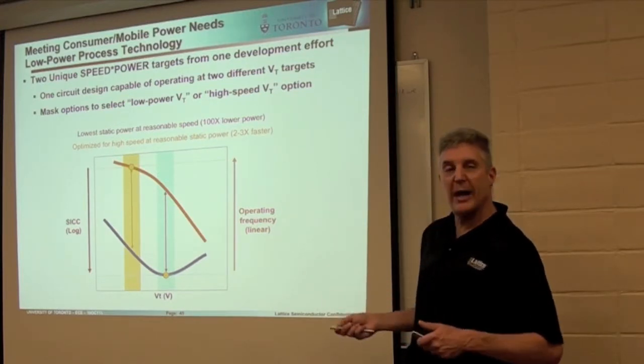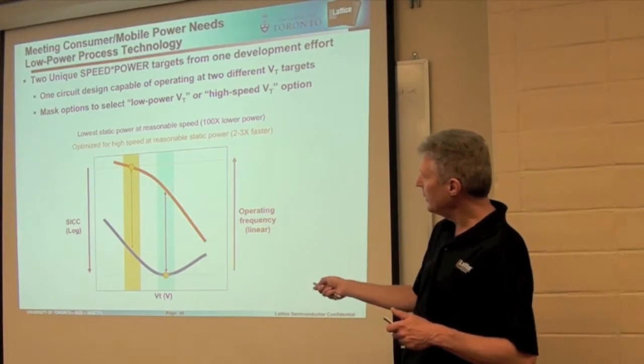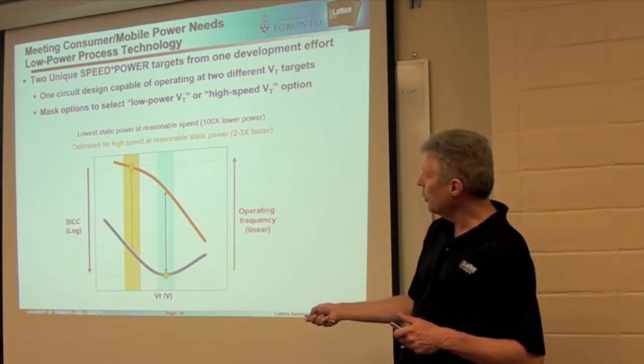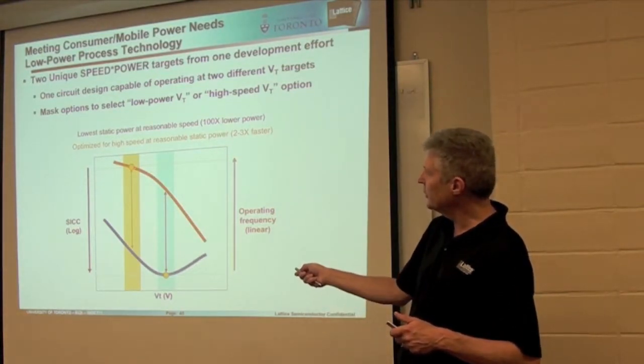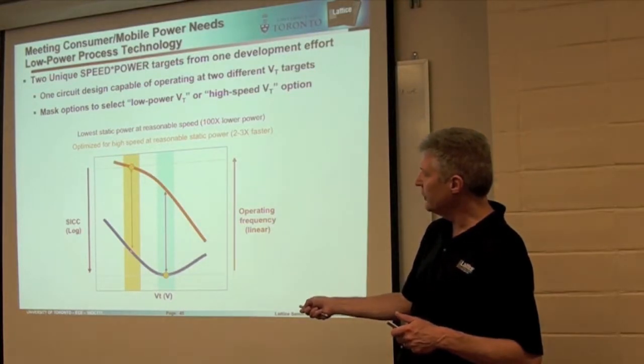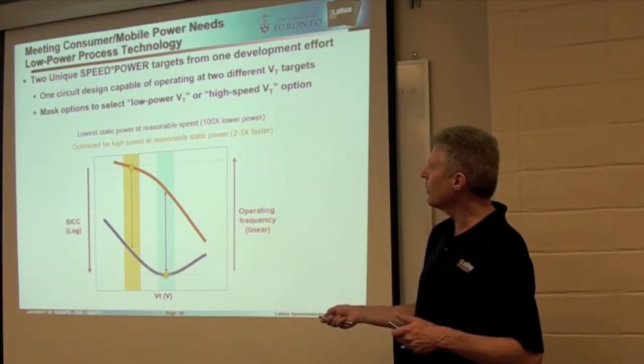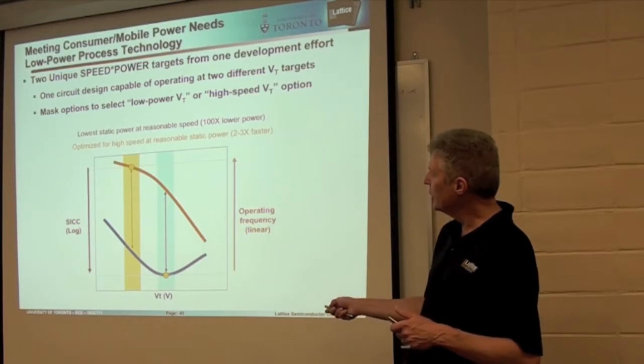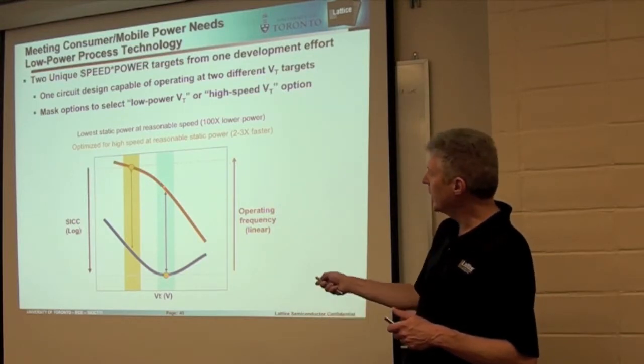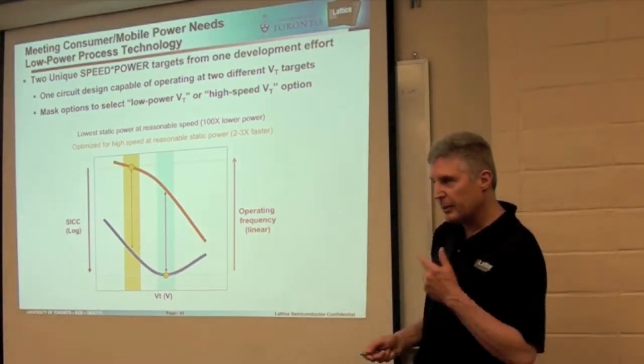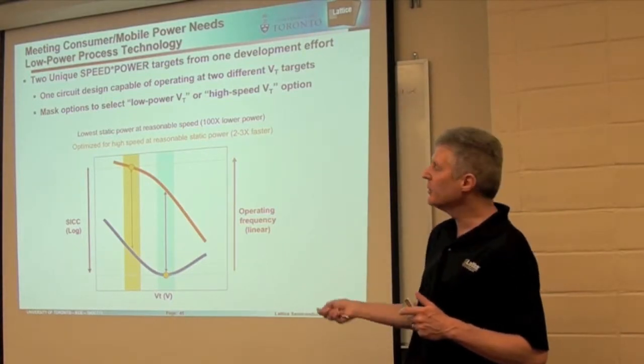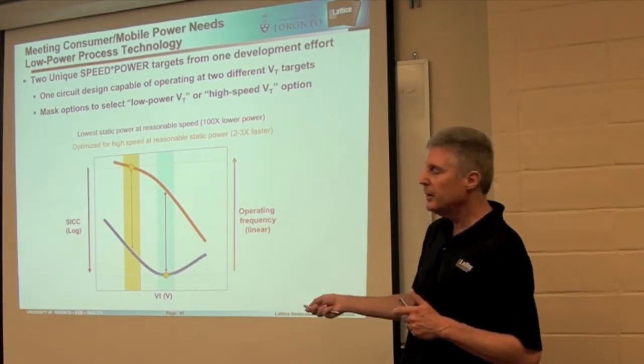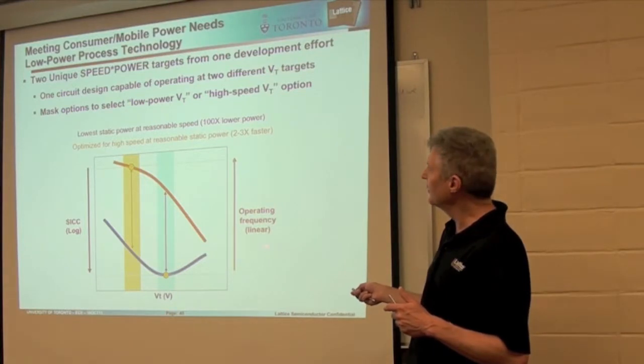operating frequency, or how fast the chip will go. So this is speed and power. And you can see at low threshold voltage, you can get relatively high speed at a significantly higher power level, or if you go to higher threshold voltage, you can get a very low static power at a somewhat reduced operating frequency. Importantly here, the power scale is log, and the operating frequency scale is linear.